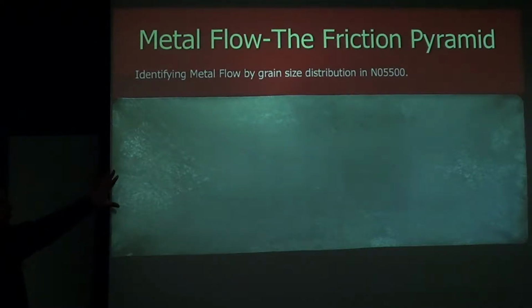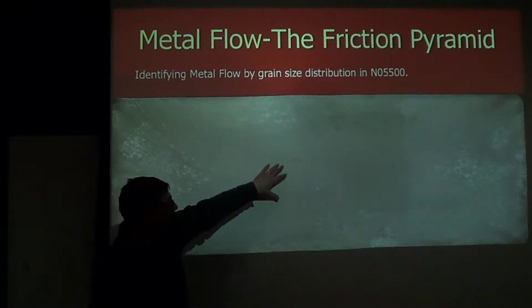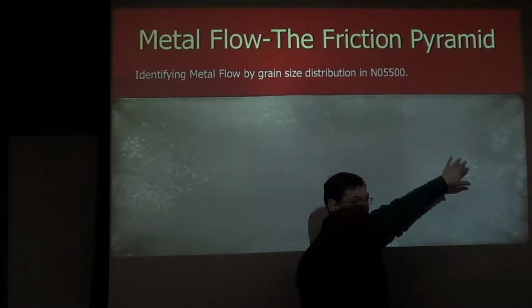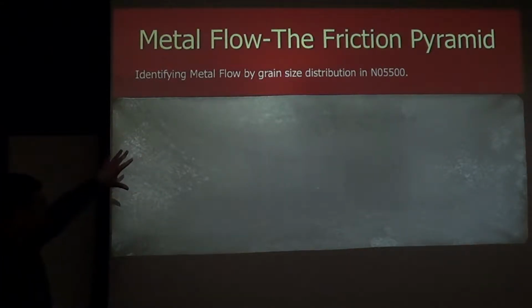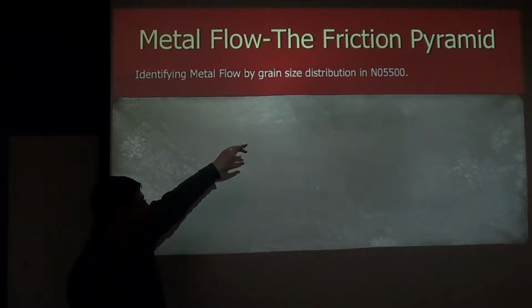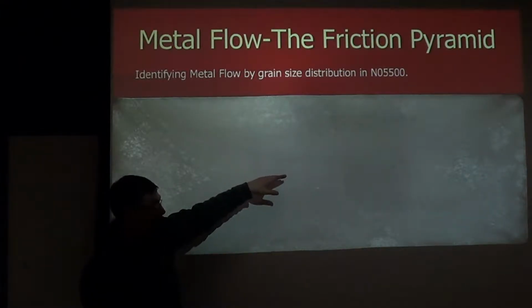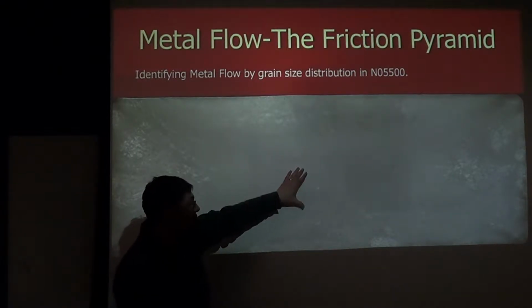To show that from a different single alloy now, not a layered piece, this is a nickel alloy, and you're seeing the same effect, but this time illustrated by differences in grain size. Again, uniform in cross-section, but very fine grain through this area, and where we have the white speckles, we have larger grains. The metal was affected differently where we had no friction and we had friction. In this particular case, they brought the press down, and initially there would have been material that was not influenced by friction, and then eventually it was. The material on the top and bottom that was affected by friction kind of collided with one another, and then you did get some deformation of those regions.